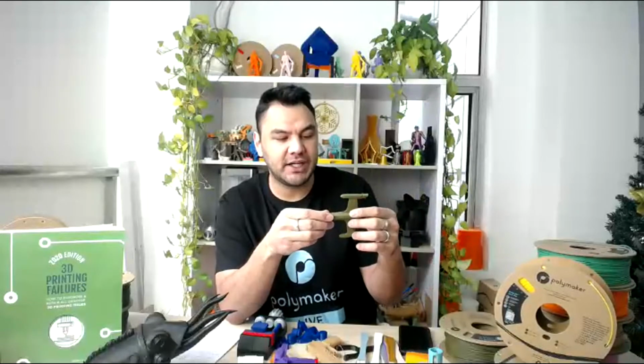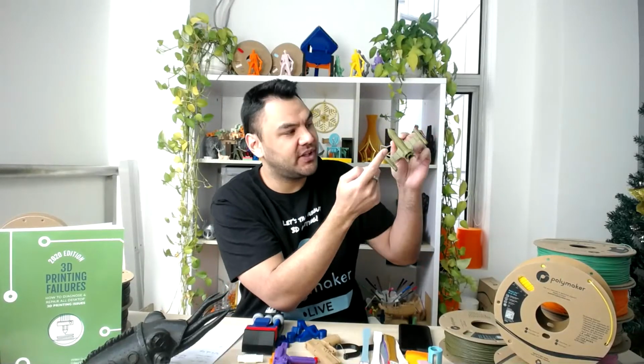Collie Logan: woodworking also has a problem with directional strength. Yeah, definitely, and that's exactly for the same reason. When you have alignment of the polymer, then you have the same problem. If you have strength perpendicular to the alignment, then it will be very weak. But if you have strength parallel to the alignment, then it will be very strong. And for wood it's the same. Why? Because wood is also a polymer, right? It's cellulose, and this cellulose is aligned. It's all of these cells that are like this. So if you are hammering a nail through the wood, then most likely you will start to see delamination following this fiber, in exactly the same way that if you put a nail through that print, you will have delamination along the layers. So a very good analogy with the wood.